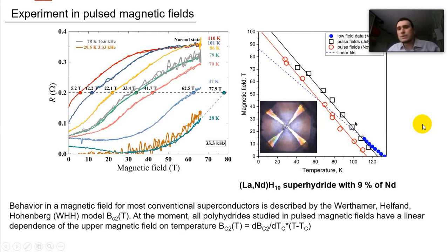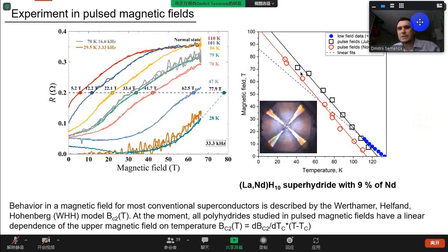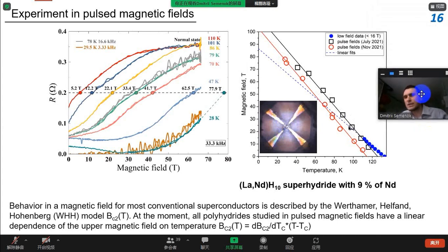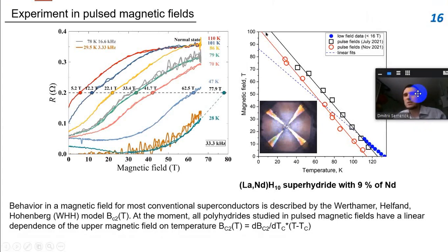We saw that, so this curve is called the magnetic phase diagram. For superconductors, we see that this is pretty linear. This characteristic is a little bit unusual. Not all superconductors can demonstrate such linear behavior in a strong magnetic field. So it shows the dependence of the critical temperature of superconductivity on magnetic field. And on the left side, you can see the actual original data. It's the resistance of the sample versus the magnetic field applied.